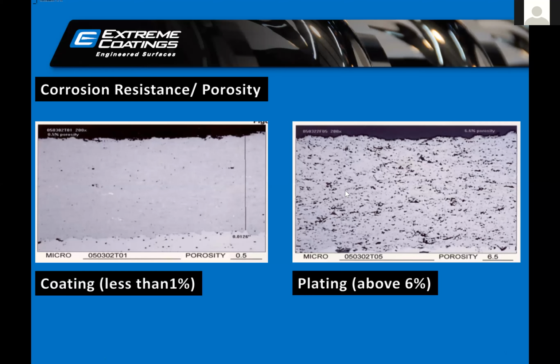When plating or coating is done, the porosity factor is very important. For example, if this is the plating I have done on the screw, acid can enter from this connected porosity and it can still attack the base metal.